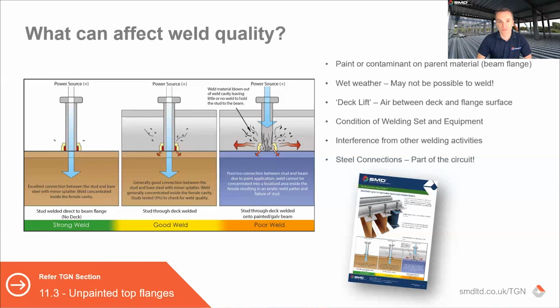So what can affect those settings? What can affect the weld quality? What might cause a stud to fail in terms of the weld itself? You could have paint or contaminant on the beam, between the deck and the beam. Wet weather, where it hasn't been dried off correctly. What they call in the industry deck lift, so that's basically air or a gap in between the deck and the top flange of the beam. That can create, as you're welding, more porosity in the weld that essentially then causes failure when you test the weld. It could be to do with the welding set and equipment.